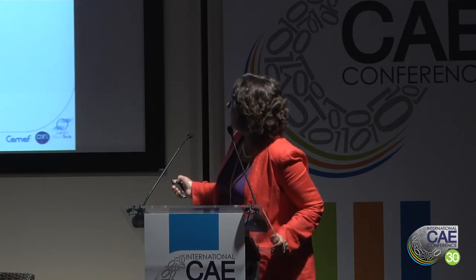So it's important to be able to simulate this evolution of microstructure in real operating conditions, or the closest operating conditions to real life. So we discretize the part with different grains, and we can also have a small particle inside the classical grain in order to see the influence of this second phase particle in the microstructure evolution.